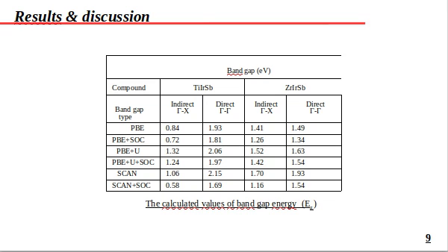And it's clear that using PBE+U and the SCAN functional gives a better description of the semiconducting behavior for the two compounds, where both approximations open the gap between the valence and the conduction band, while the inclusion of spin-orbit coupling decreases the band gap value for all approximations used in this section.